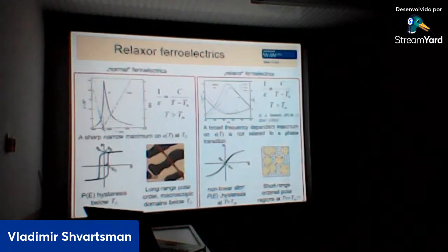So, relaxor ferroelectrics. What are relaxor ferroelectrics? I think for most of you, it's a new term. So, normal ferroelectrics, I already introduced: materials which have spontaneous polarization, which can be switched by an electric field. And these materials have a long-range polar order below the Curie temperature. We can see macroscopic domains, regions with polarization, for example, in one or in the opposite direction. And typical dielectric permittivity versus temperature for normal ferroelectrics looks like here. So we have a sharp peak at the Curie point, and above this Tc, our dielectric permittivity follows the well-known Curie-Weiss law.